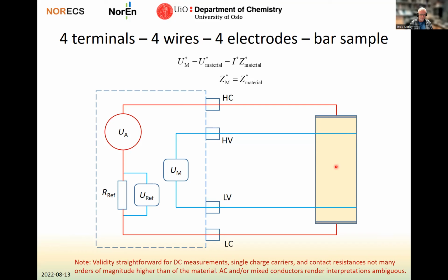If you use AC measurements, the 4-electrode measurement becomes ambiguous because of the different time constants of the electrodes and the material. And if you have mixed conductors here, it is not obvious that the current running reflects the true transport number of the different carriers and the true sum of conductivities, because the electrodes here may have a different transport number than the bulk material.